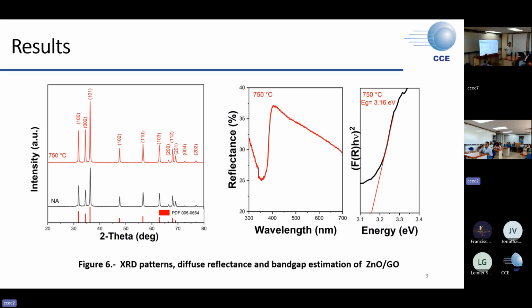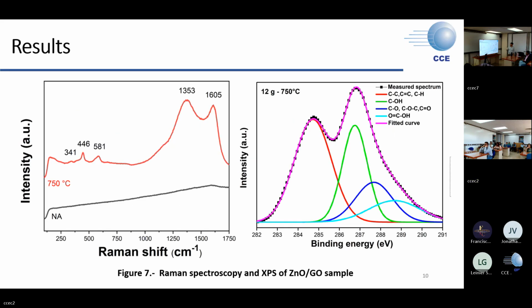This was the first time that I suspected something different. The zinc oxide powder directly from the microreactor was brown, so it had a lot of organic content. Once annealed, the powder was gray. That is the reason the band gap is smaller.